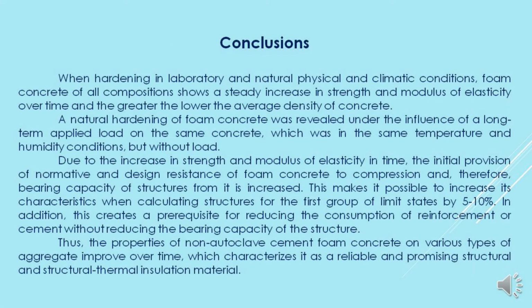Conclusions. When hardening in laboratory and natural physical and climatic conditions, foam concrete of all compositions shows a steady increase in strength and modulus of elasticity over time, and the greater the lower the average density of concrete. A natural hardening of foam concrete was revealed under the influence of a long-term applied load on the same concrete, which was in the same temperature and humidity conditions, but without load.